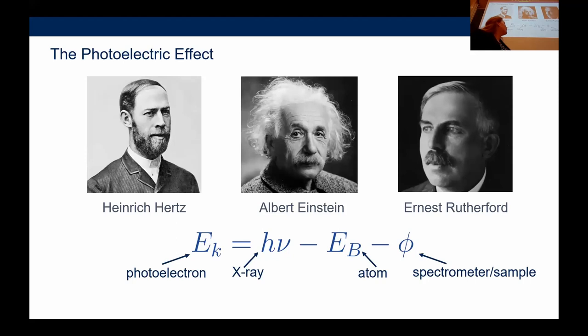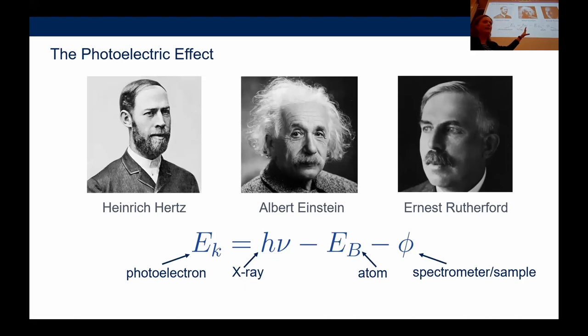All of that is based on the photoelectric effect. The three pioneers basically laid the theoretical and experimental foundations. The key point is that the kinetic energy of the photoelectron is what you measure, the X-ray energy is what you set — given by your source, whether lab or synchrotron — and that is related to the binding energy within the atom. There is also the work function of your spectrometer or sample, which will shift all your energy scales. If you do your experiments right, you can control that, leaving the binding energy as the one big unknown we're always trying to determine.